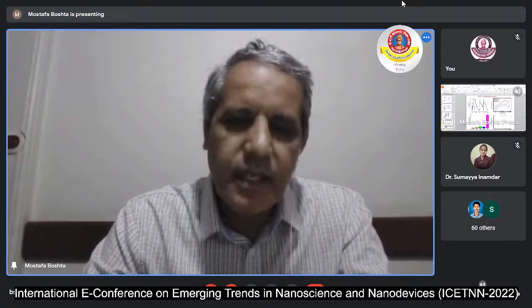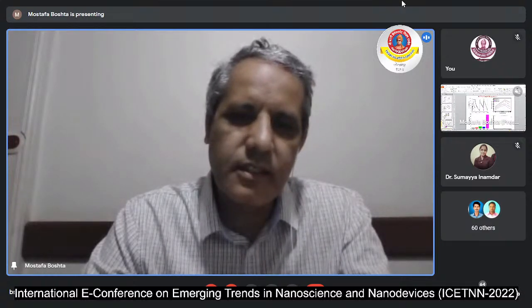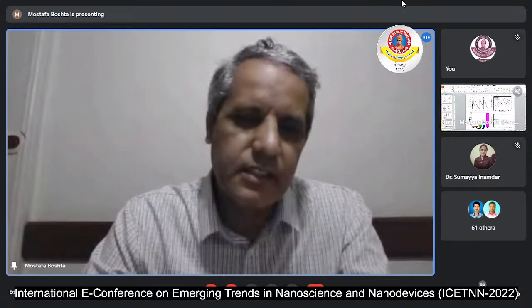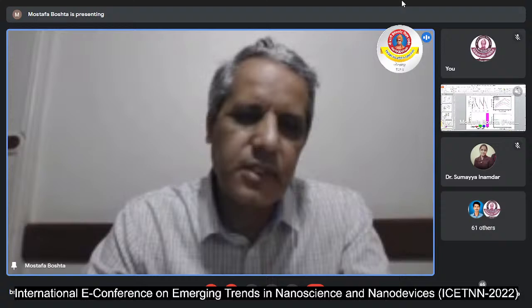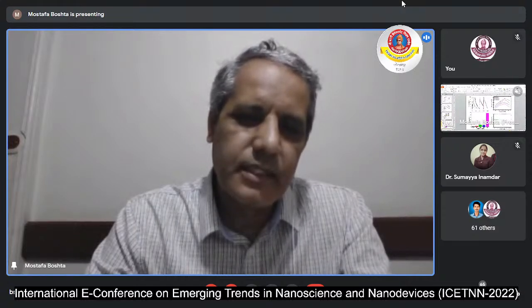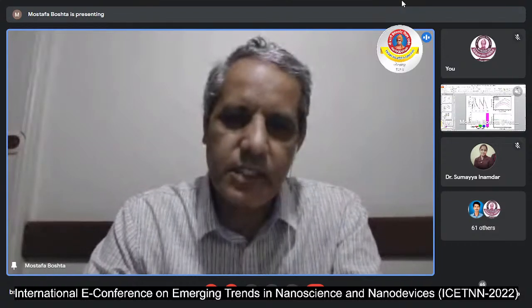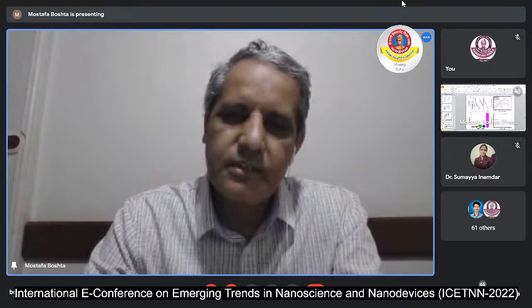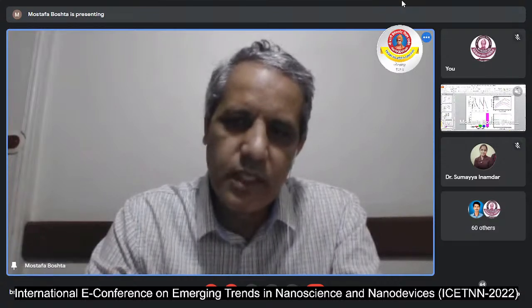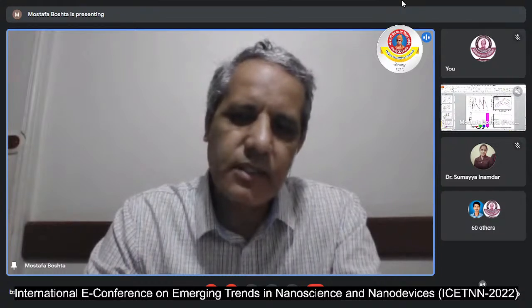Also, we use the nickel oxide material for NO gases, nitrogen oxide gases. As we can see, this measurement is done in Sweden, at Linköping University, when my PhD student was there, and you can measure ammonia gases as a detection by nickel oxide. As we can see, the dynamic of the detection of nickel oxide with ammonia, and we have different material thicknesses, and we can see that the sensitivity increases when the thickness is very low, and also the temperature is not high, mostly towards 200 degrees.